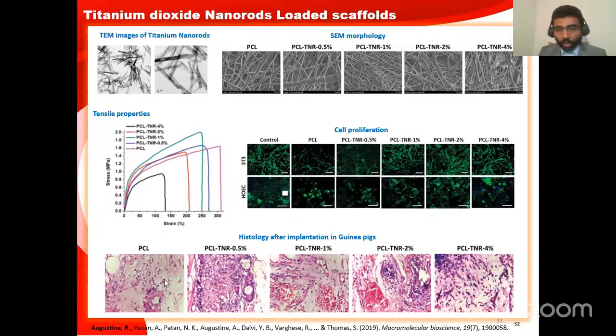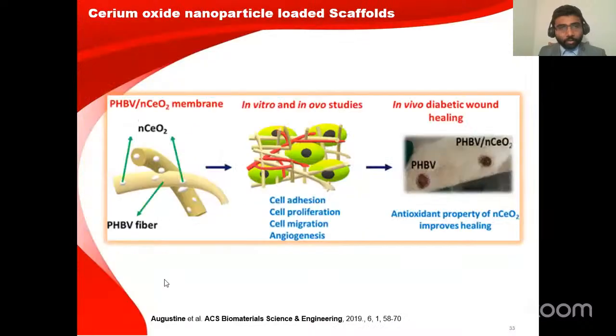Because of the time limitation, I'm not going through in detail. Also, we used cerium oxide, as I mentioned, an antioxidant nanoparticle, in polyhydroxybutyrate valerate scaffolds. In the fibers, the nano ceria were loaded. Then in vitro and in ovo studies were performed. In ovo means chicken embryos. Then we found higher cell proliferation, cell adhesion, cell migration, and blood vessel formation, which resulted in higher wound